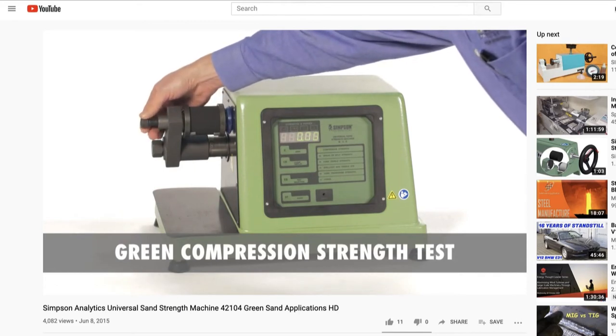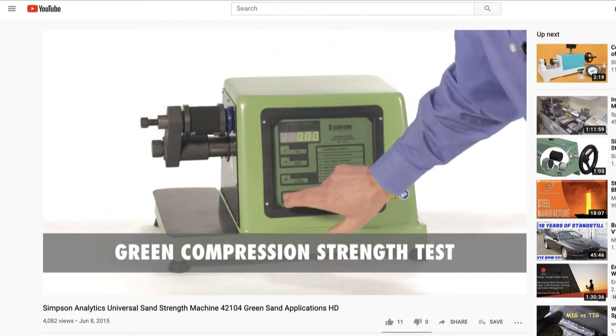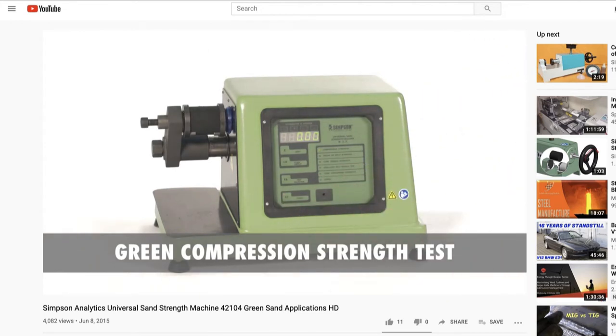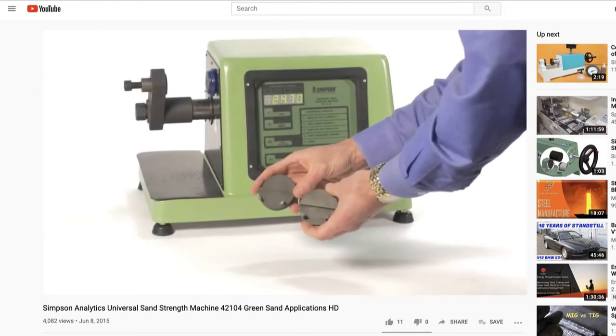So this is the one that you guys are going to do, the green compressive strength. Make sure that you can put a preload on, but then turn the preload back to 0 and then hit the test. It's one thing you might not have done. So this particular one has like 24 psi.